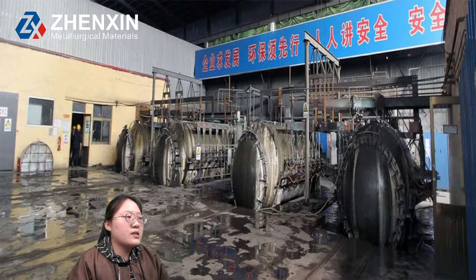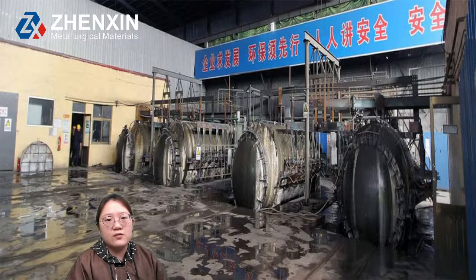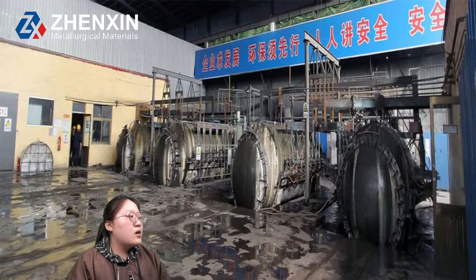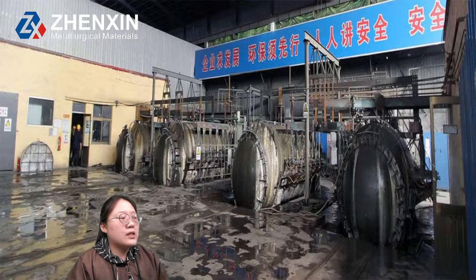It's added as a component of chrome manganese and chrome manganese nickel stainless steel to replace the shortage of nickel. Research shows the role of nitrogen in expanding the austenite region is about 30 times that of nickel.